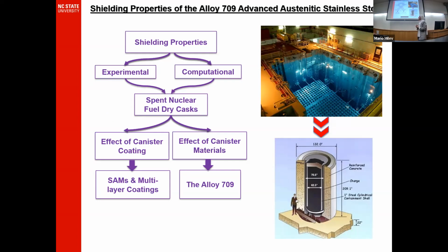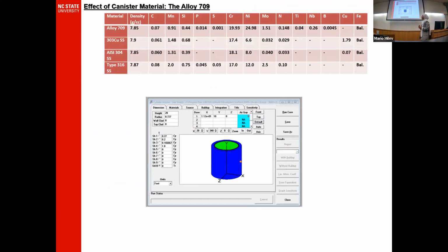I also studied different coatings, like newly developed self-assembled monolayers and multi-layer coatings used as a coating for the canister. For the canister material, I studied alloy 709 compared to 303 copper, 304, and 316 stainless steel. They have similarities in composition, but also some differences which can be related to their different behavior. I performed this study computationally using Microshield.